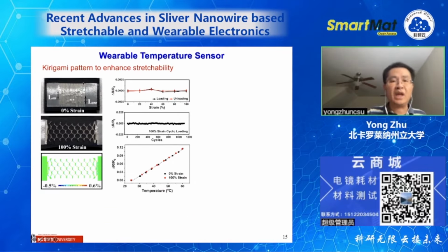So we use a kirigami structure to achieve that. Essentially, this is the sensor. When we stretch it, you see all these ligaments deform out of plane. Then we performed finite element analysis. For 100% applied strain, the local strain is very small, in the range of minus 0.5 to about 0.5%. Very, very small, you can see. That's why we also measured the resistance change. You see the resistance change is nearly zero, almost zero.